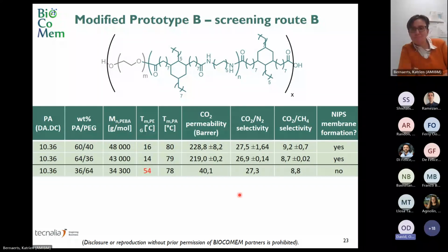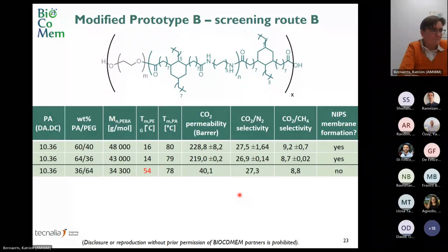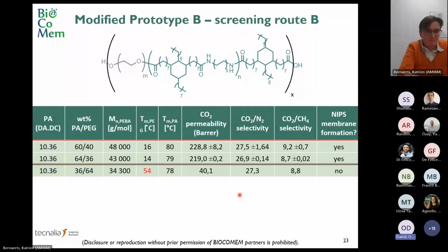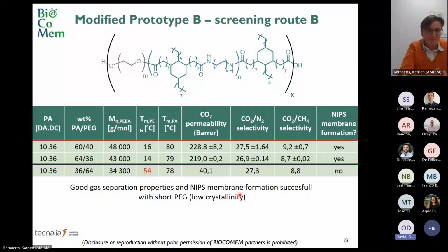Yeah, so once we had these very nice polymers with a higher molecular weight, we tested more than one film for gas permeation. This is why you can see plus and minus. This is the standard error. So what we see is that we have a good permeability. It's comparable between the first two polymers, and the selectivity the same. And then when we have this higher melting point polyether glycol, we have a much lower carbon dioxide permeability. And then with the first two polymers, we managed to make nice porous flat sheet films.